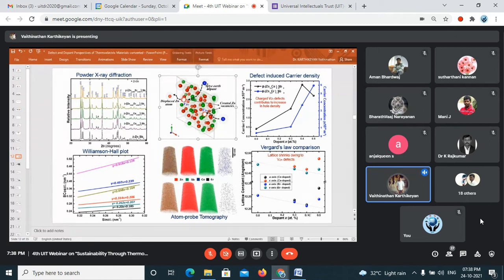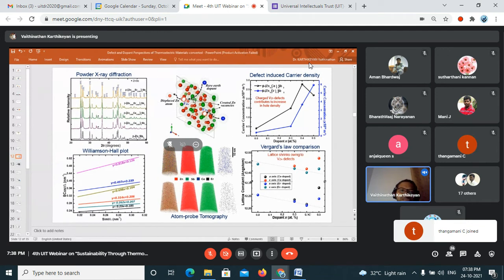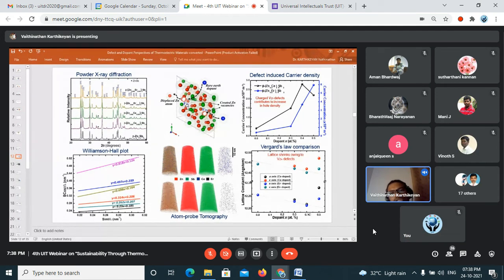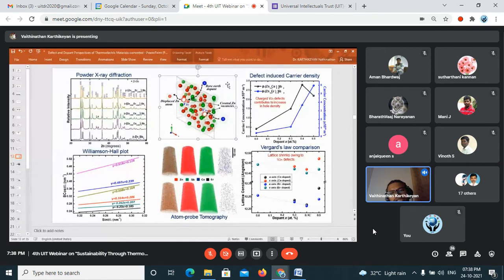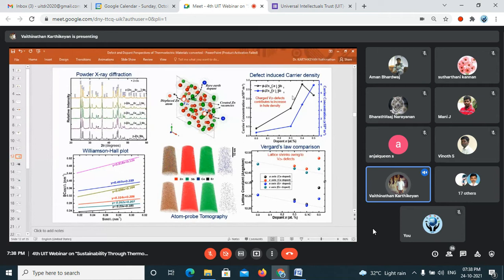This illustrates the mechanism: the size of the rare earth dopant increases and causes the zinc vacancy defect. And here the thing is, this zinc vacancy is a charged defect, which causes the increase in the hole concentration of the material, which is being observed in the Hall measurement.